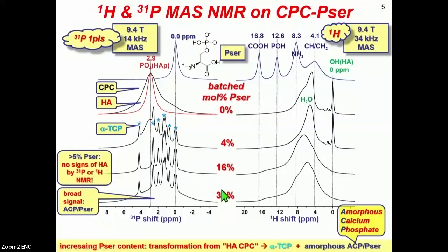Then for larger phosphoserine contents, there is no longer any evidence of apatite, and what rather forms is a very broad resonance that stems from phosphates in amorphous environments, and that goes for organic as well as inorganic ones. So we refer to this cement component as ACP-PSER because it consists of a separate phase where amorphous calcium phosphate is intimately integrated with the phosphoserine molecules.